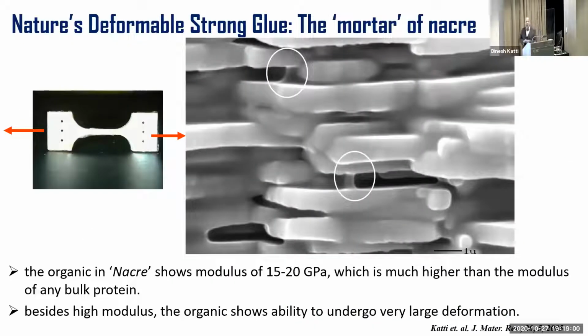But while we were doing our experiments, we found something else, which was very interesting. The mortar between the bricks was very stiff. It had an elastic modulus of 20 gigapascals, so it is a very, very stiff material. And typically when a material is stiff, it is brittle.